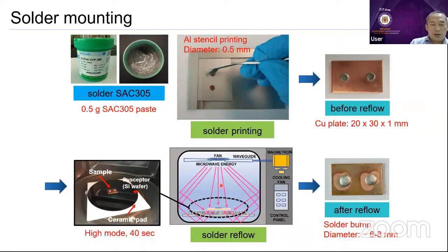There is two-way heating here, as I explained before: directly to the samples, and then heat from the substrate, the silicon wafers. At the end of the day, this is our solder. You can see that they start to melt and form bumps, something like this.